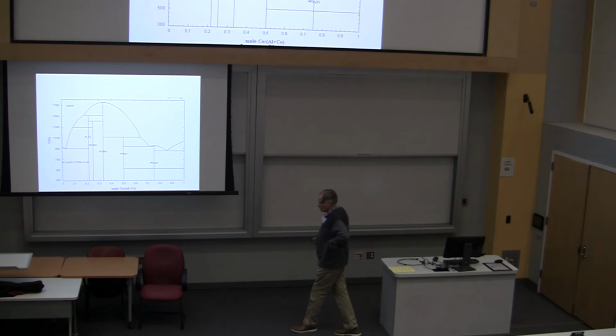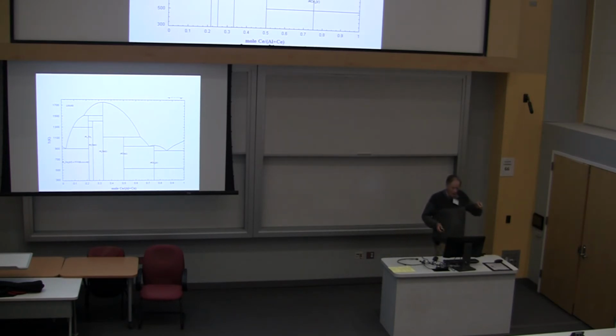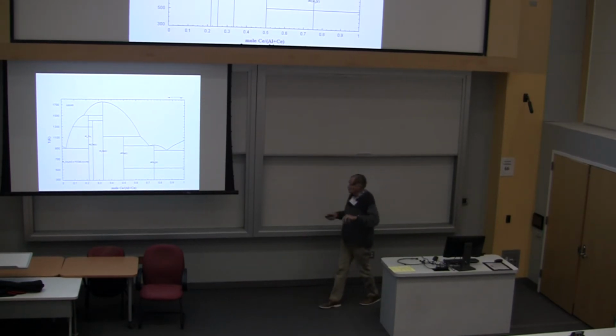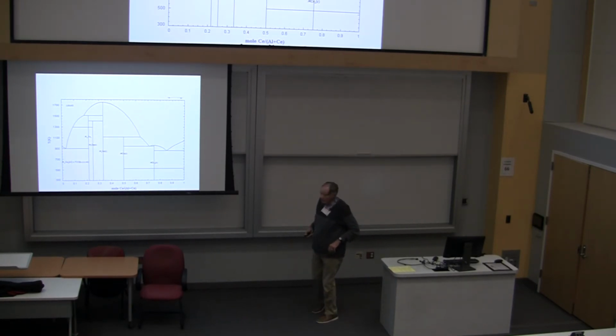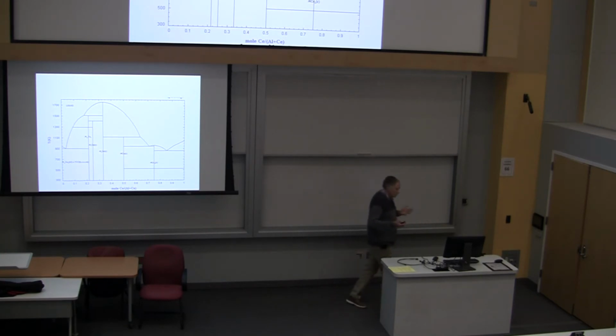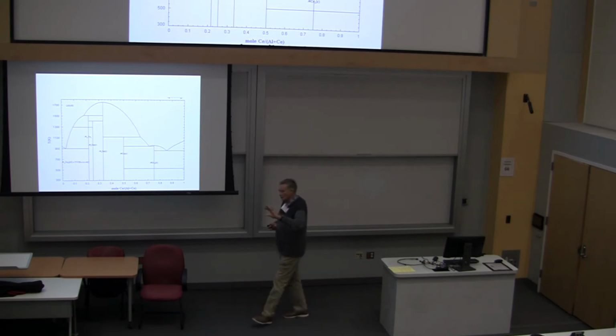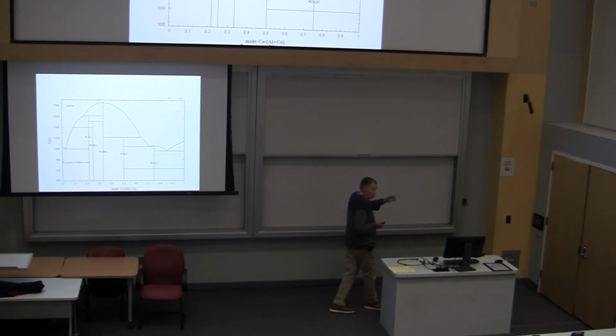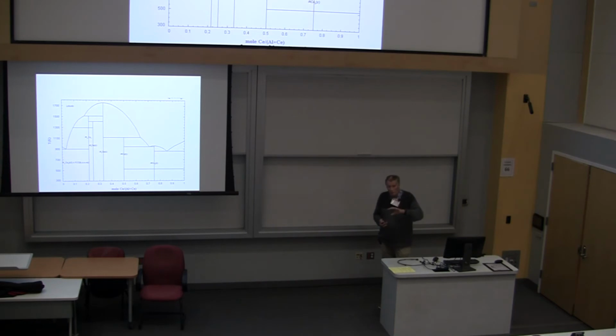And the way that strain annealing works is you can distort something, or even just arc melting and the cool down puts strains in, and then you can sit somewhere under the melting point in here and anneal things in. For example, pure rare earth elements, almost all of them, are hexagonal or some form of hexagonal, double hexagonal, but they go through a cubic phase at high temperatures, right? So if you take a rare earth and you want a single crystal of the hexagonal phase, you can arc melt it and then anneal it, say, at 1200 degrees in a quartz tube wrapped in tantalum foil to keep it from reacting with the quartz tube.